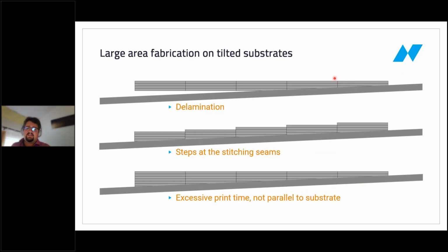Typically, there are two ways to avoid this. Either you measure the correct height in each field individually, and then you can have a structure that is well connected everywhere and has roughly all the features represented, but you will get these steps at the stitching seams, which can be problematic for optical, mechanical, all kinds of applications. Or you make a thick socket below it, and then it's okay, you don't get delamination, but you lose lots and lots of volume that you put down basically in vain, and still the structure is actually not parallel to the substrate surface.